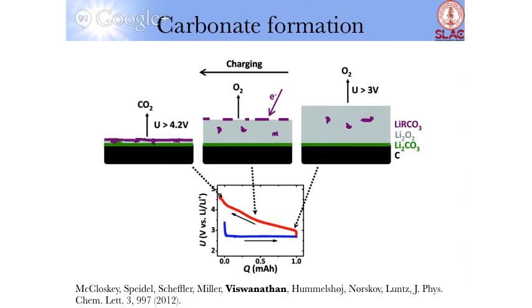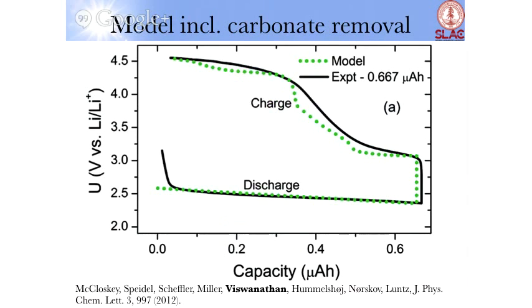It's always good to take any story and put it into mathematics, so we turned this into a mathematical model and compared against electrode measurements. What you see is that the features are reproduced. The model predicts that the rise in potential is essentially due to this decomposition reaction closing active sites. You have this rising potential until you reach a point where you have lithium carbonate, and that has to come off — which happens at about 4.5 volts.